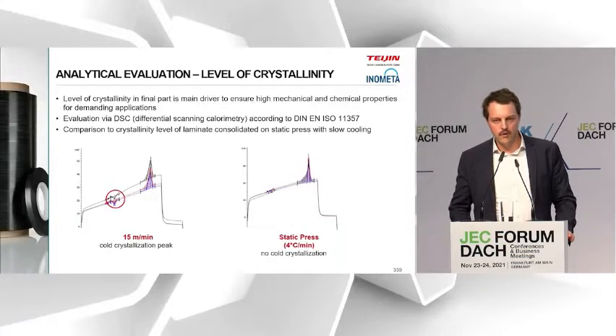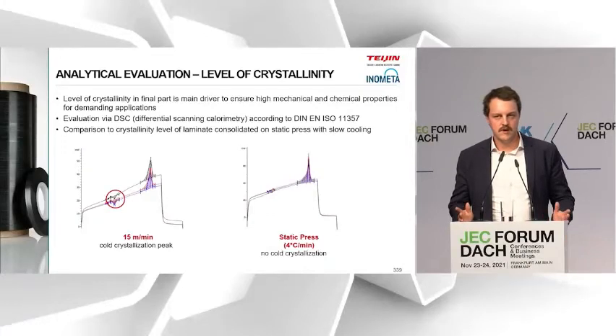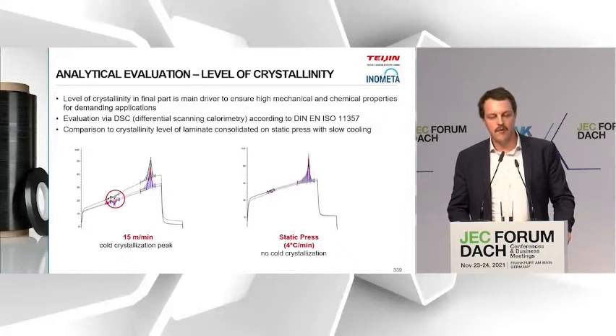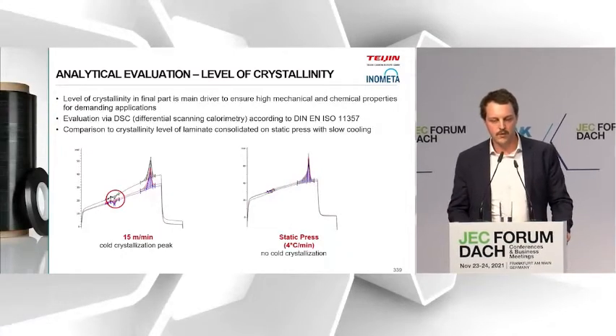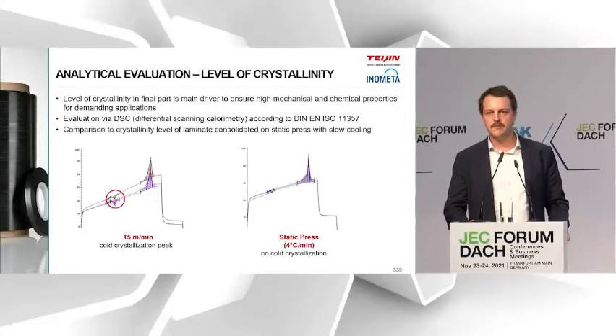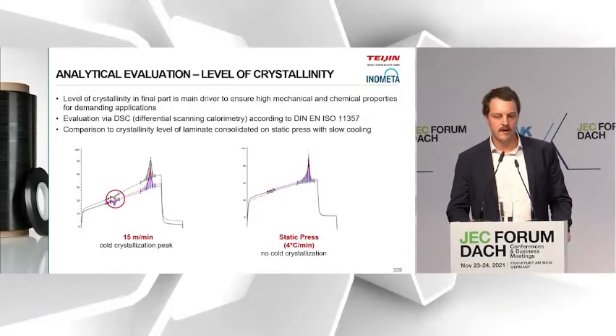What we did is, for all the trials, we did separate runs of DSC analysis. Not sure how familiar you are with that sort of analysis. So basically, it's a thermal analysis method where you compare a reference sample with the actual sample from the part and can get a good feedback of the thermal history the part saw, and then you can see different effects such as the melting, what you see on the right side, the high peak, or glass transition temperatures, and as well what we see on the left side, when we look at the 15 meter per minute winding speed, we have a cold crystallization peak.